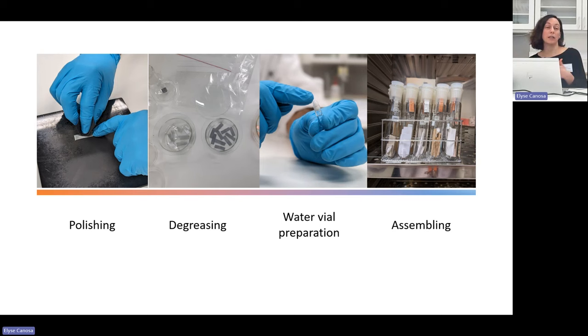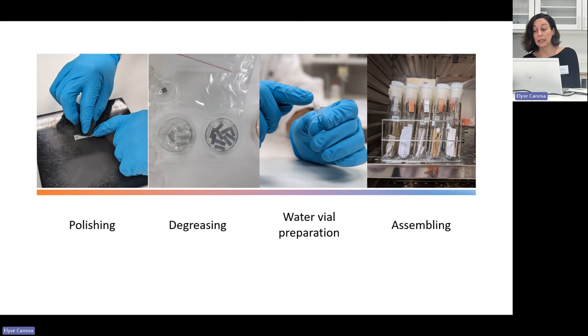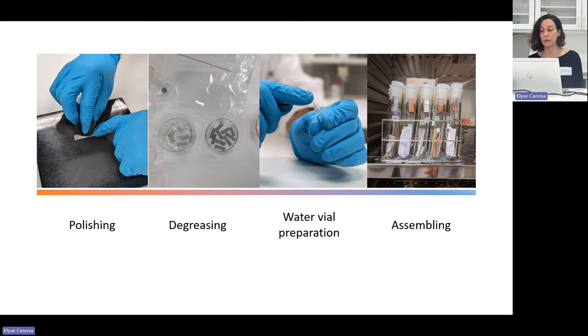Within our practice here in the laboratory, polishing and cleaning the coupons is a very important part of the process. We polish both sides of all three coupons with P600 sandpaper until each surface appears evenly polished, removing any native surface oxides and giving them a more reactive surface. Lead in particular can develop a blue or purple surface oxide in storage over time, so we try to remove that to expose the more reactive surface underneath. After polishing, we place the coupons in an acetone bath. When it's time to insert the coupons into the stopper, we remove them and dry them using lint-free wipes, then place the tubes vertically in our oven.